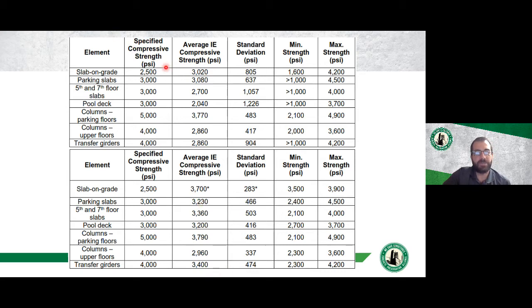And so here we can see here's what was specified in the original drawings. And you can see things like for the pool deck. The pool deck was 3,000 PSI, but we're measuring it's around 2,000 with damage. But when we remove the deteriorated concrete locations, we see that in sound concrete, the compressive strength was 3,200 PSI. So when the concrete isn't damaged, yes, it is meeting that 3,000 PSI. But obviously, when there is damage, we're weak. That concrete is much weaker. And so effectively, we can look at what the compressive strength of the sound concrete is, and then also the effect of the damaged concrete.